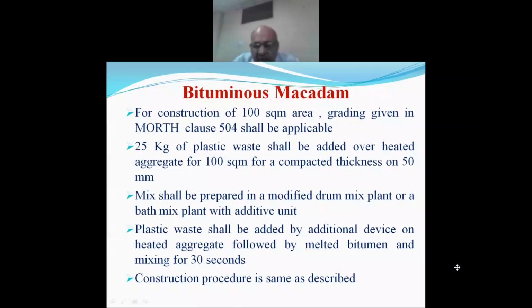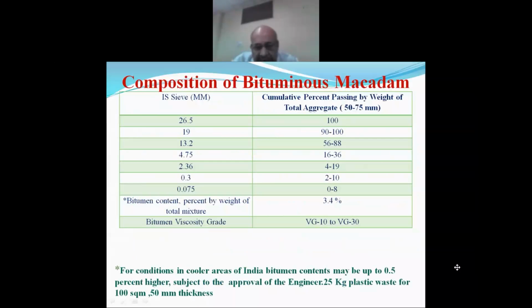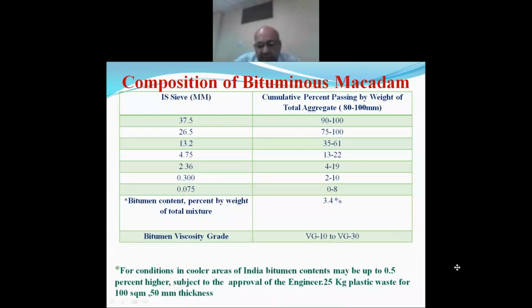The procedure for mixing is the same as conventional construction of BM, DBC, MSS or SMA. In case of the bituminous macadam, BM modified with plastic waste shall be constructed as per MoRTH clause number 504 in a thickness of 50 to 75 mm. Modified BM shall be used for upgradation work for strengthening if traffic is more than 1 MSA. For cold climate areas, 0.5% extra bitumen will be used.